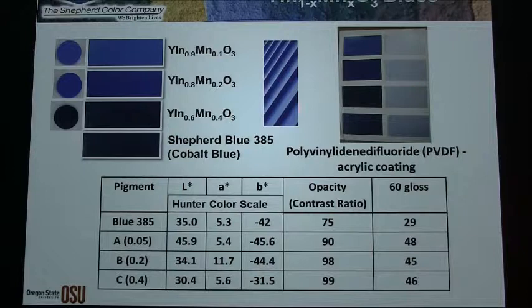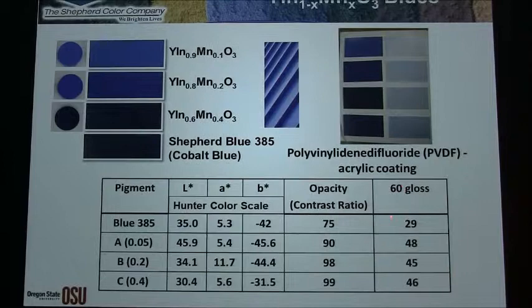So you can see the comparison. The most important, forget about this color scale, are the opacity and the gloss. The opacity of our pigments is very high. Only one coating is enough for 90% to 99% hiding power, whereas the cobalt blue is about 75%.